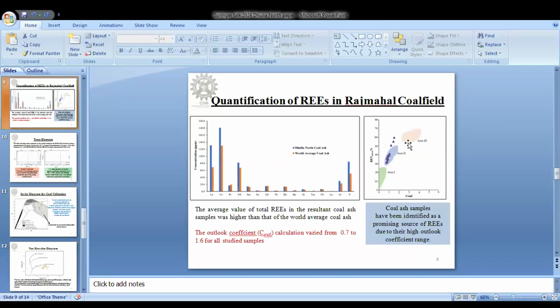Now, when we look at the quantification of rare earth elements, as you can see from the first graph, the orange one depicts the world average for coal ash, and the blue one is from this particular coal block. So it is significantly higher than the world average. And in particular, I would like to point at some of the important ones such as cerium, lanthanum, neodymium, and yttrium and scandium. These five rare earth elements are actually important.